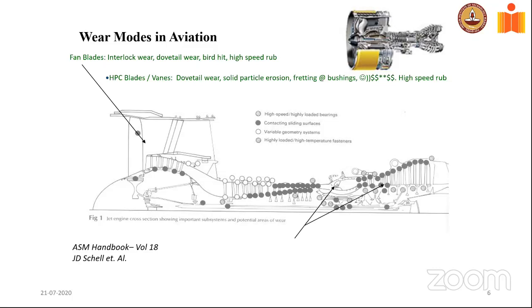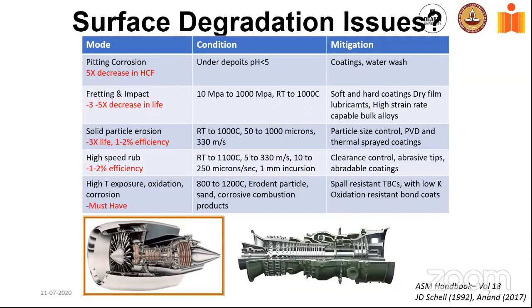And the temperatures range all the way from room temperature in the front of the engine to around 650 degrees Celsius midway at the compressor exhaust, and then to around 1100 degrees Celsius on the high pressure turbine section, which again decays down to maybe around 700 C as you exit the engine. So why does it matter? I'll ignore the line on pitting corrosion. It's a different mechanism. But when I look at fretting and impact, we can see a 3 to 5x reduction in life. Looking at solid particle erosion, there can be a 3x reduction in life. There can be a 1 to 2% drop in efficiency. Look at high-speed rub, you have a 1 to 2% drop in efficiency. And then you have high temperature thermal barrier, which I would leave for now.